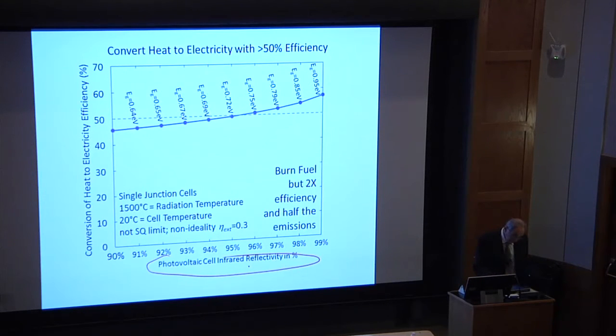And so the efficiency, if you get above 96% reflectivity, the efficiency goes above 50%. So the efficiency tends to be between 50 and 55% efficiency. Now, if you burn fuel for the heat, which you can do, you would burn half the fuel. Okay, so you'd have half the emissions. So if you burn fuel, but you could use the sun for the heat.